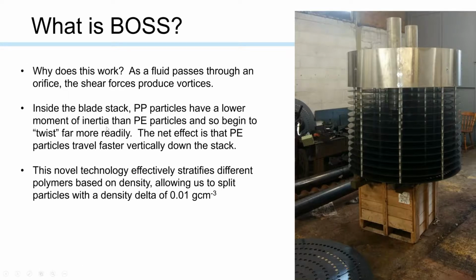That's just another picture there. And then just highlighting again that for the rigid plastics, we are able to separate particles with a density delta of 0.01 grams per centimeter cubed. So it's an incredibly compact system. This stack that you're looking at was a Mark II stack that we had 2 years ago, and it was able to deliver 6,000 tons per year on a single shift of recycling capacity. So extremely simple, very passive design. There's only one moving part, which is the eccentric camshaft that drives this up and down.